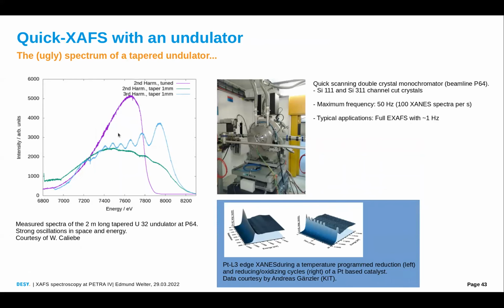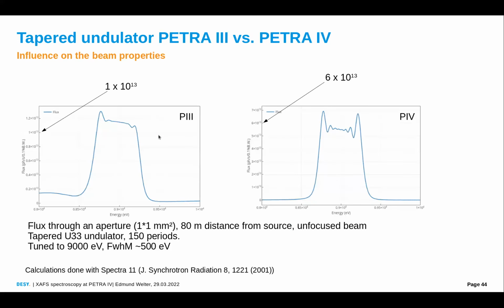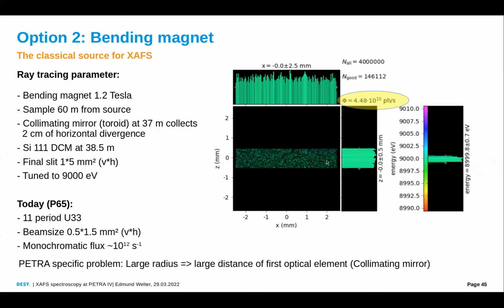We see these oscillations in reality, so we can expect that this is also real and that the problem becomes more severe in the future. The second option, as I already mentioned, would be to use a bending magnet, but as a simple matter of fact, there's simply not enough flux. We are too far away from the source to collect enough of the divergence to get enough flux on the sample, especially if we really plan to do XAFS at that beamline. So this is not an option which we seriously discuss.